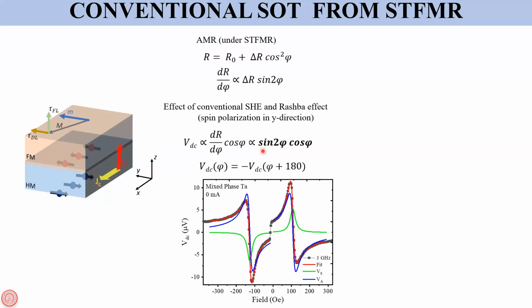dependence. By the way, the sin 2phi part is basically coming from the AMR, because this voltage is detected due to the AMR in this structure. So this is an indication of conventional spin orbit torque, where the charge current flows along the x-axis, the spin current flows along the z direction, and the spin polarization is along the y direction. This is shown in this figure here.